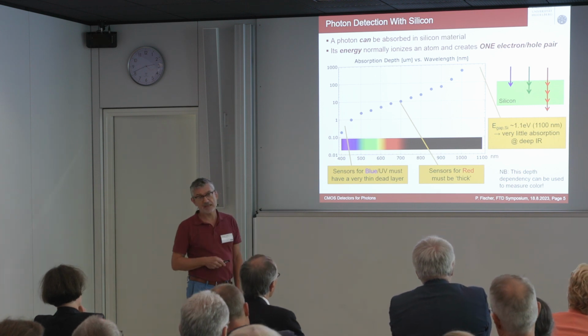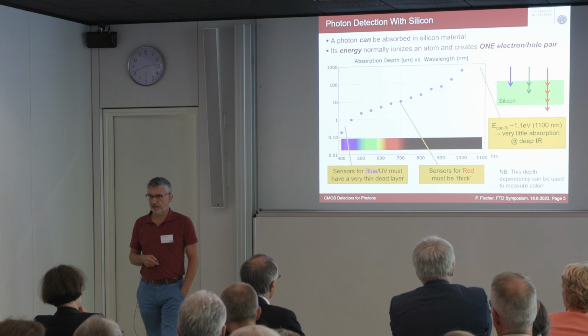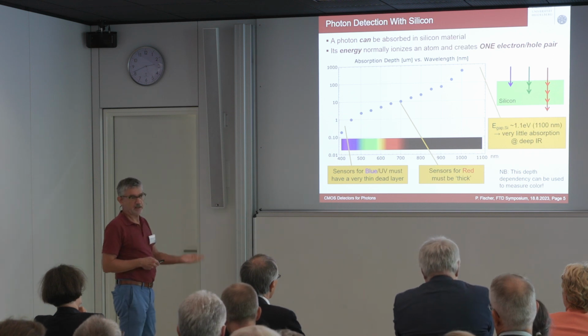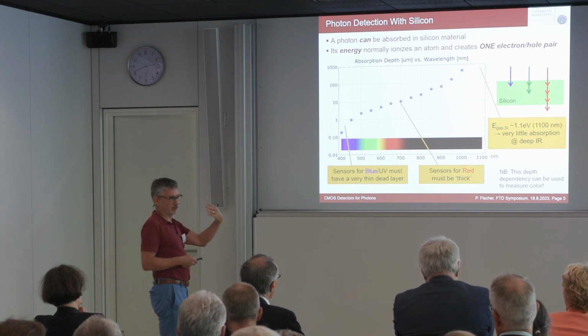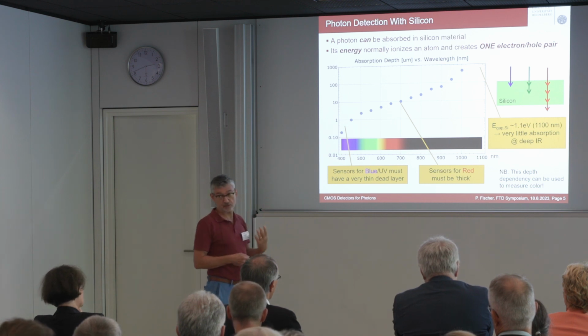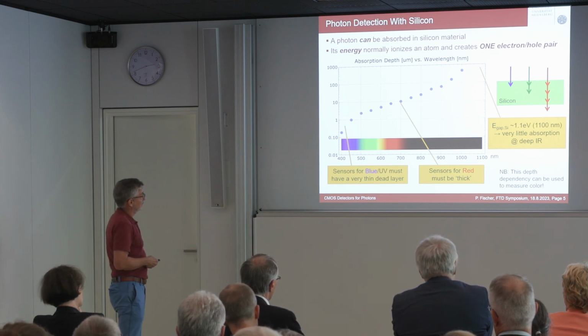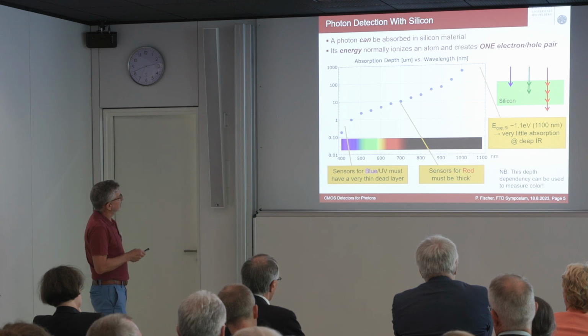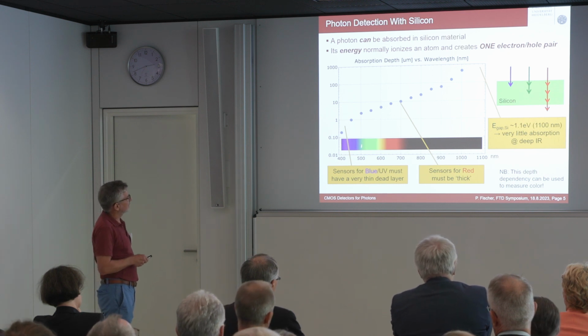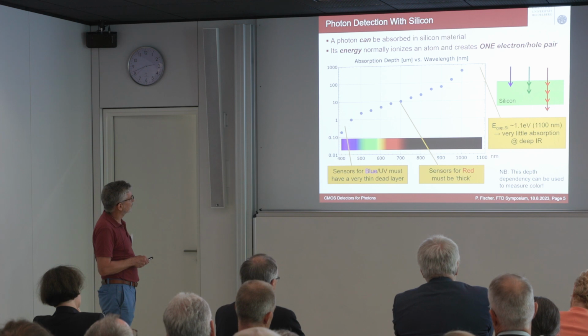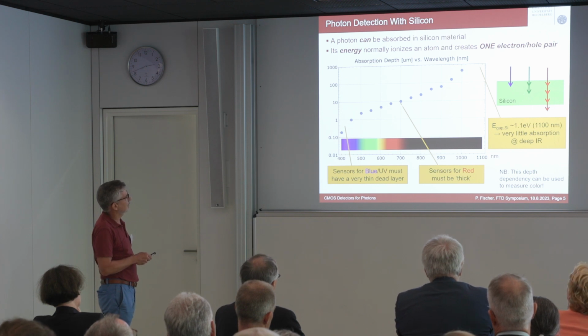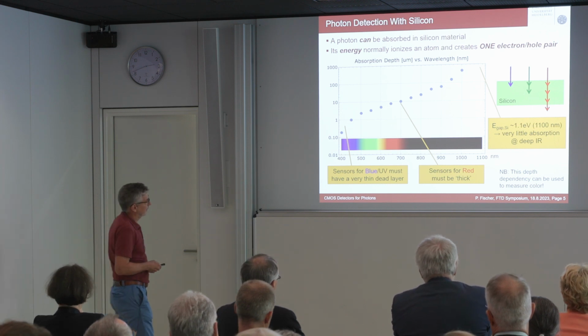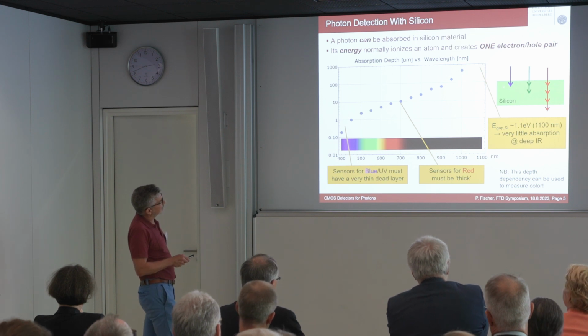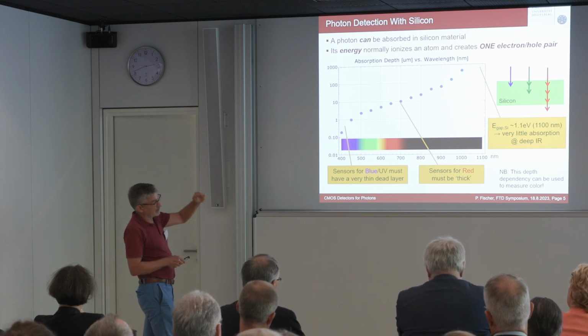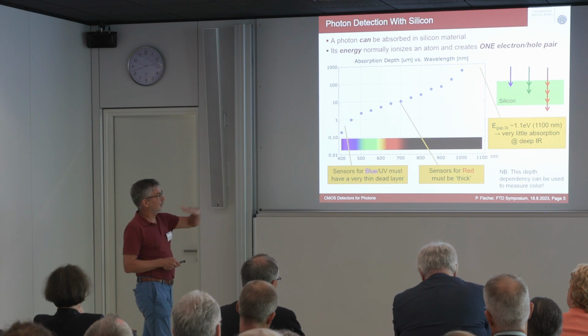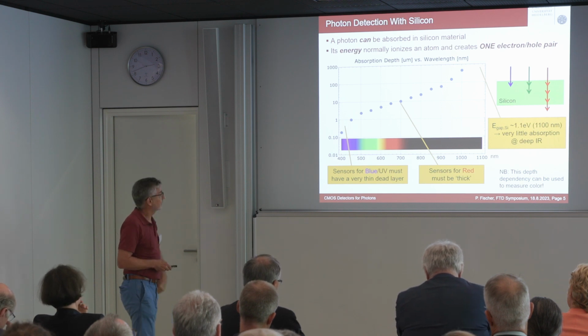That's a pity, because many technical applications use infrared light, like telecommunication, or LiDAR, because you want to use laser light, which is not visible for the eye, and you cannot use silicon for this process. But the message here is that silicon is quite good for green light, because the penetration depth is reasonable, let's say. And by the way, there are detectors which measure the absorption depth in the silicon and then can infer the color of the light.